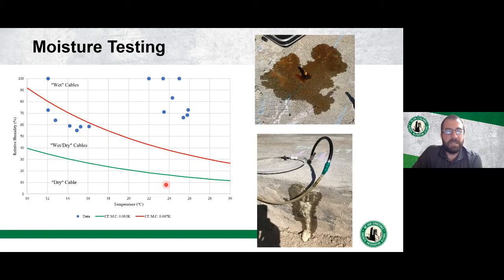So here are some results of that testing. So here we have the temperature and the relative humidity of the air coming out of those tendons. And you can see above this red line, the tendons are considered very wet. In here, they're kind of wet, they're moist, and then below the green line, they're dry.